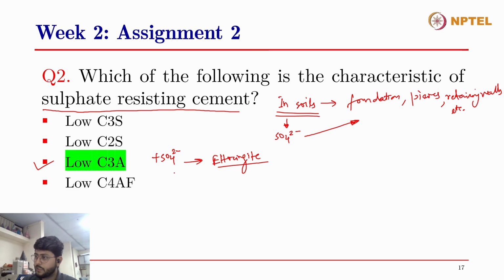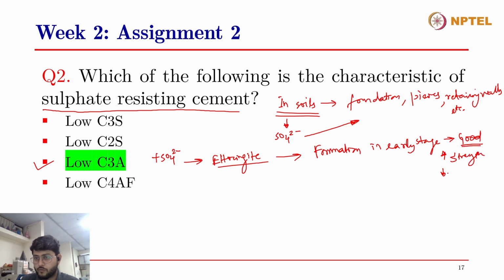Now, when sulfates are introduced to the concrete structure at a later stage, when the concrete has already hardened, then if there is a high amount of aluminates in your system and some of the aluminates are still unreacted, this sulfate will come in contact with these unreacted aluminates and react with water in order to produce ettringite at a later age. Again, ettringite is a crystalline material and will occupy a higher volume, but now the concrete has hardened and there is not enough plastic nature of the concrete to accommodate the expansion volume due to the formation of ettringite.